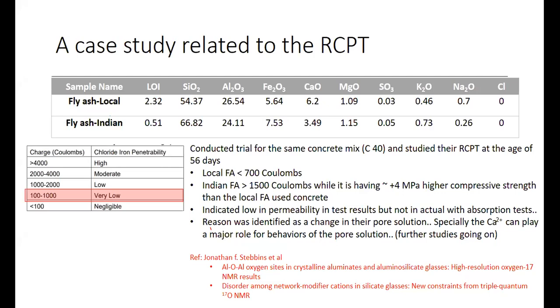The coulombs means the number of charges passed. We know Q equals I times T, where Q is the number of charges, I is the current in amperes, and T is time in seconds. Finally we get the coulombs. In the RCPT test, if the number of coulombs passed through the concrete element is between 100 and 1000, they call it very low permeable concrete in terms of chloride ion. And if it goes beyond 1000 up to 2000, it is called low permeable in terms of chloride.